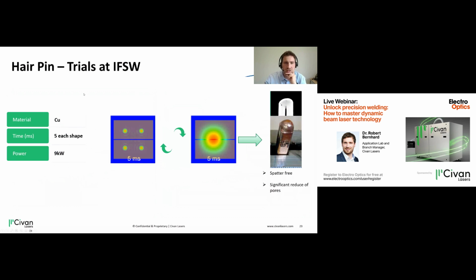This is also true for some hairpin welds we did. Here it is set up in a way that we have a beam shape set up directly over the hairpins, and by doing some time in this beam shape and then going over to a more random beam shape, we are also able to get the connection and the porosity out of the material without damaging the insulation and reducing pores specifically.